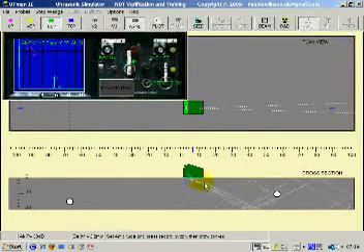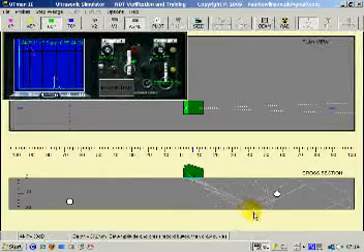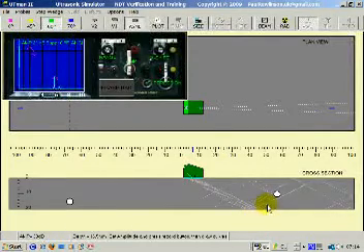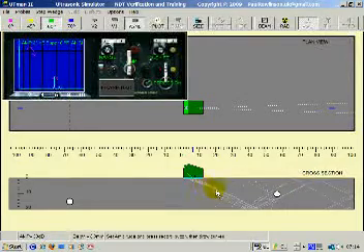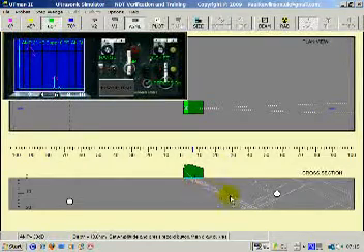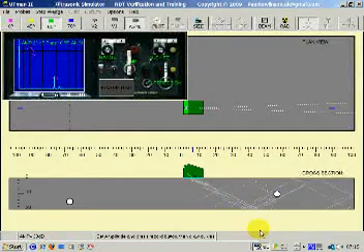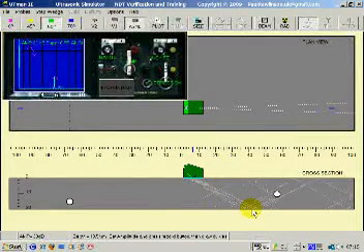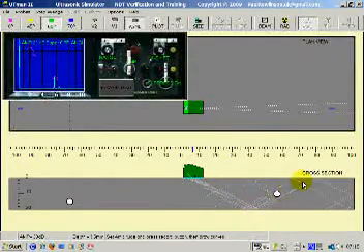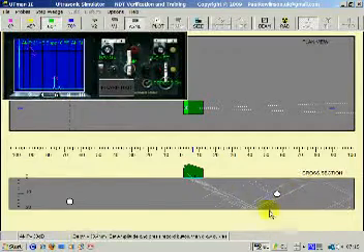The terminology is, as the sound comes down to here, that's called a half skip. As it bounces up to the top again, that's called full skip. So that's half a skip, that's full skip. Some people describe this as a leg. But certainly, most people describe this as half skip and full skip. And if it carries on, it could be full skip and a half, etc.